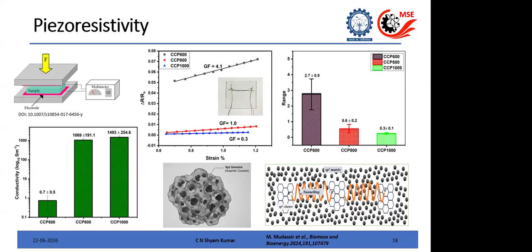That means the sample pyrolyzed at 600 degrees Celsius is more piezo-resistive than the sample pyrolyzed at 1000 degrees Celsius. Even though the graphitic content is increasing, the conductivity is increasing. So you can see this is the conductivity here. The conductivity is increasing, and from Raman we could see that the sp2 graphitic content is increasing, but the piezo-resistive response is coming down.